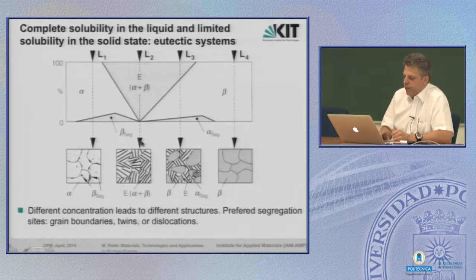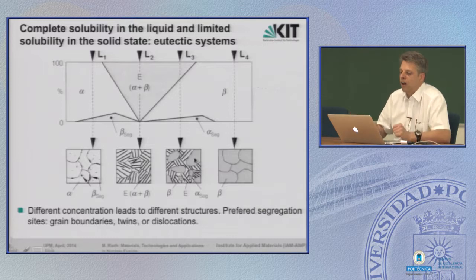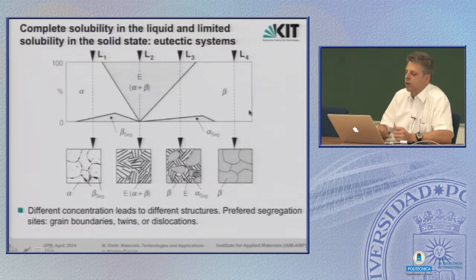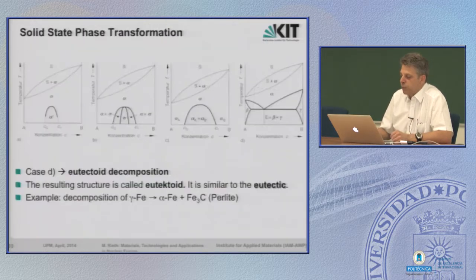That's for the exact eutectic composition. If we have a deviation from the eutectic composition, then beside the eutectic structured grains, we also have either beta or alpha solid solutes. So it's a typical two-phase material here. And well, if the concentration is high or low enough for the one or other component, what you end up with is the usual solid solute.